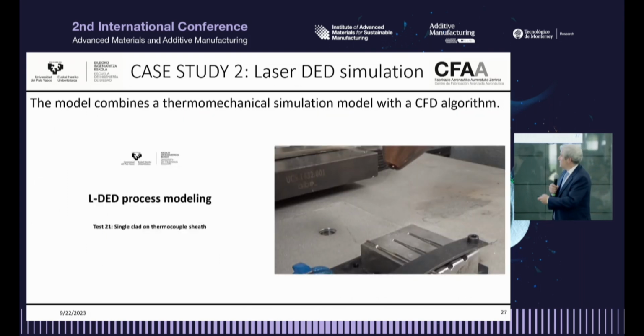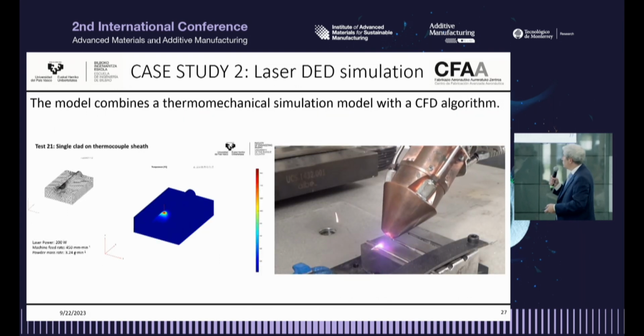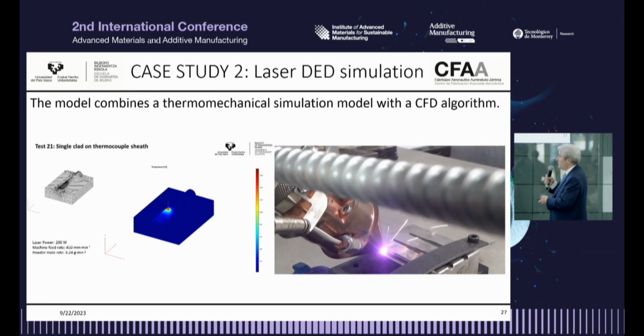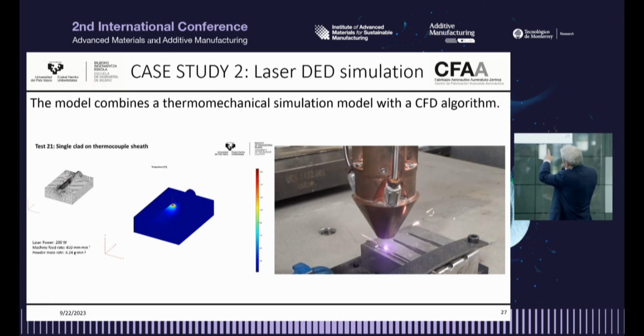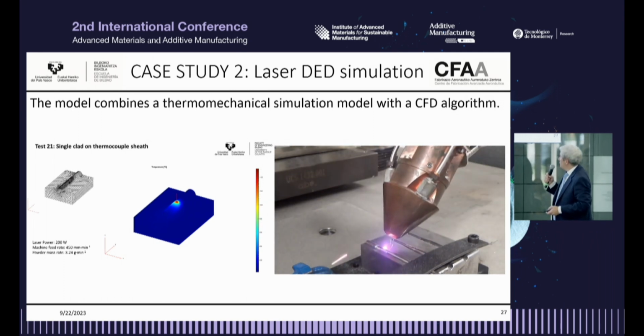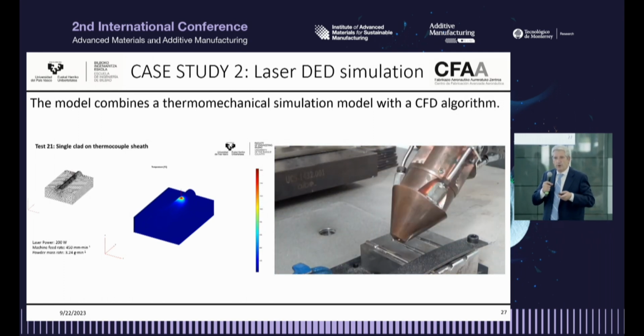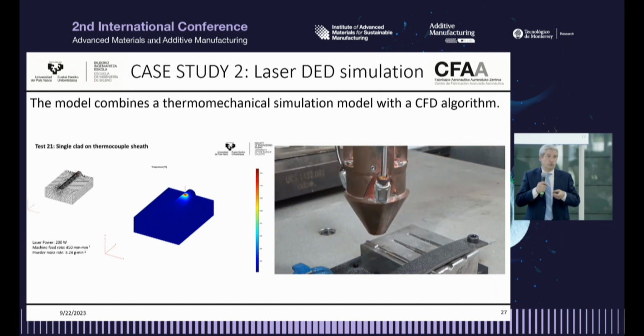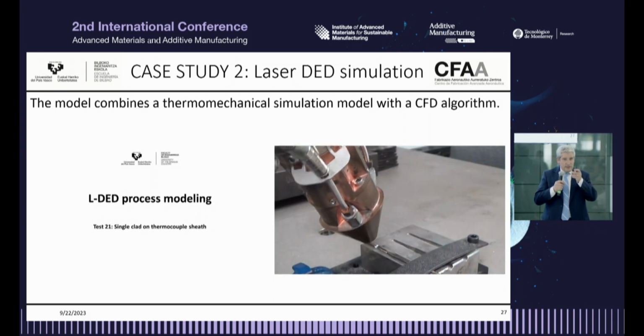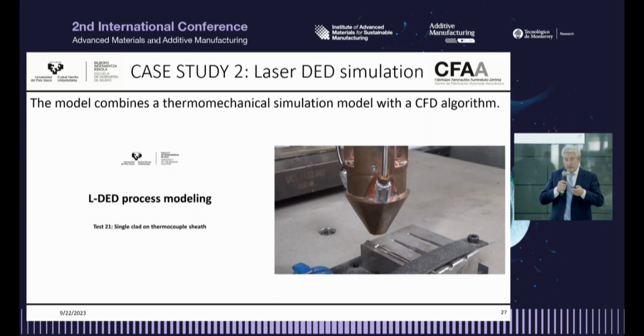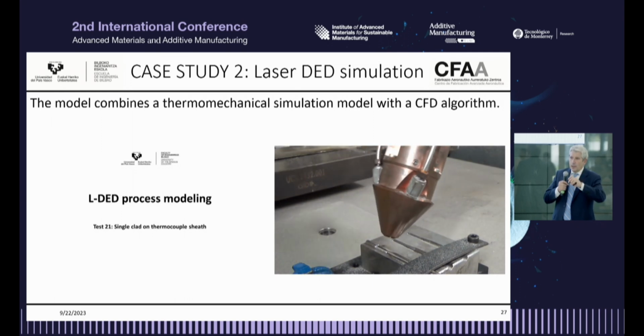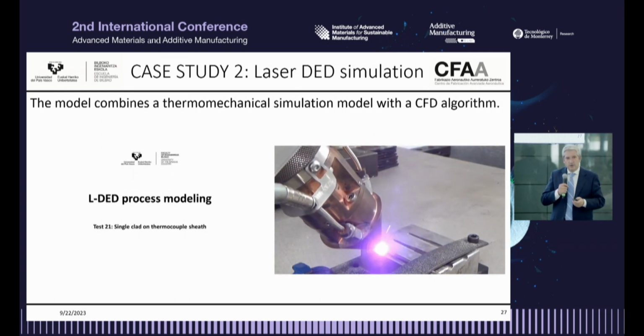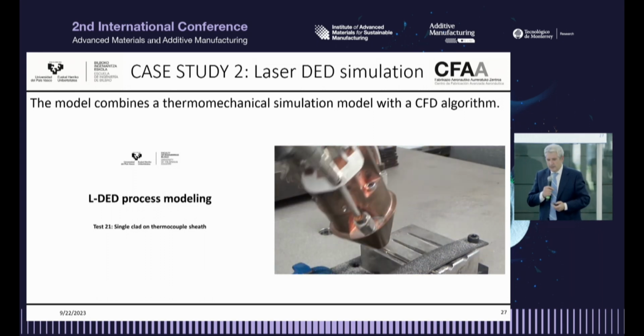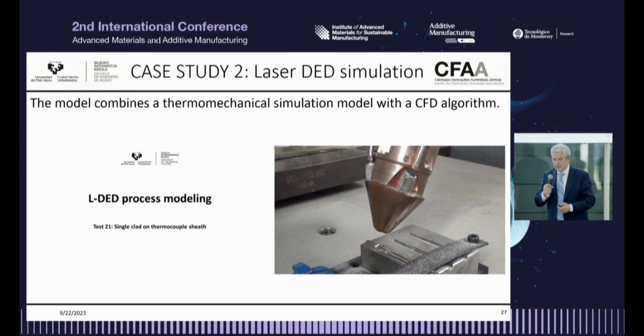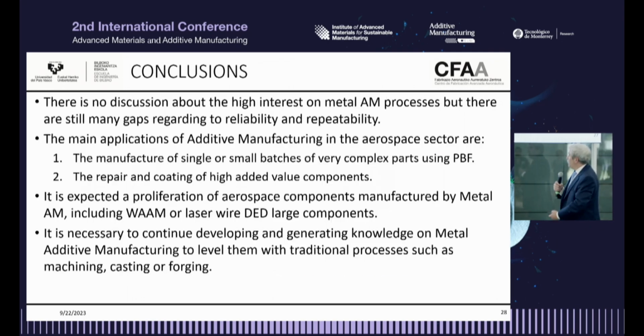And here you can see an example of the digital twin application for a thermocouple embedded into a substrate. So here we have a thermocouple, and we are depositing material there in order to embed the thermocouple into the part. And here the challenge is not to destroy the thermocouple. So we have to melt just the coating of the thermocouple, sorry, but not go deeper. So the model helps us to obtain that set of parameters. Okay, so just two examples, and just to finish my presentation, I think that I'm out of time.